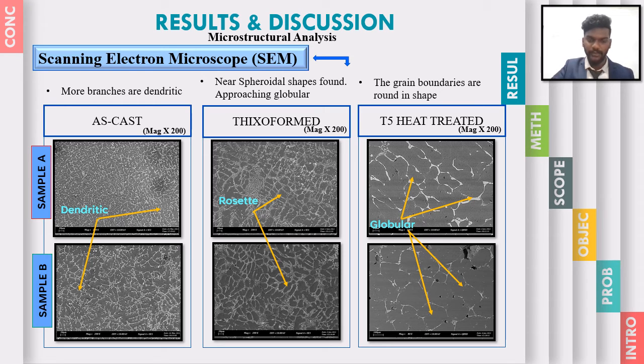For the as-cast, we can compare that A and B are similarly having dendritic structures, but the A dendritic structures are clearly visible. For the THIXOFORMING samples, we can say that both are having rosette structures, which evolved from the dendritic structure, and the thixoformed samples also show that sample A has very clear rosette structures, which are nearly spherical shapes approaching a globular structure. And for the third category, T5 heat treated samples are having globular microstructures, and the globular microstructures mostly evolved from the rosette microstructure from the thixoform stage.